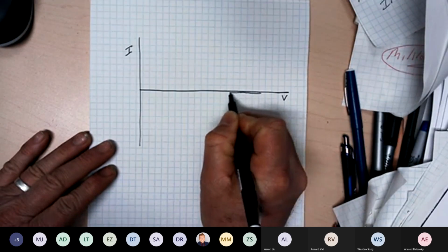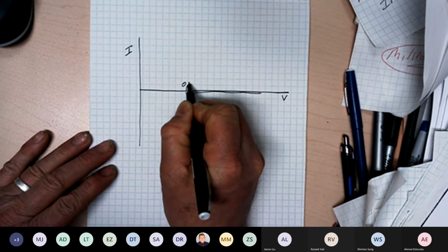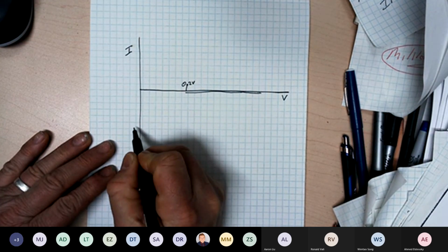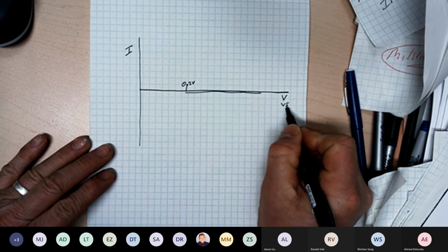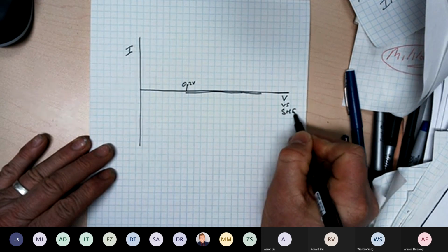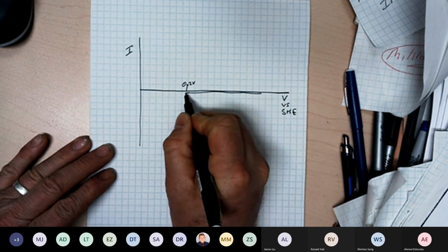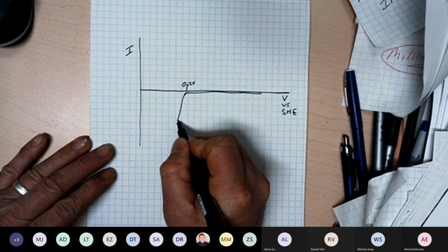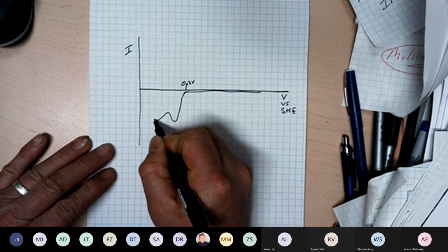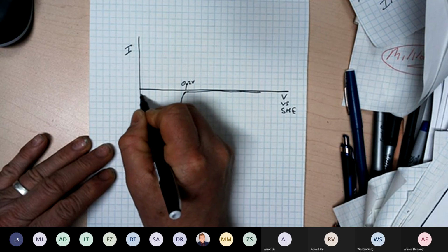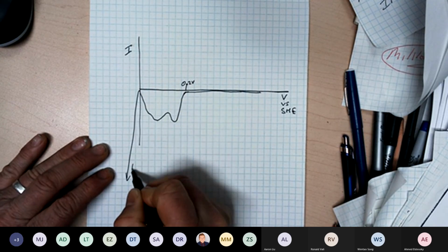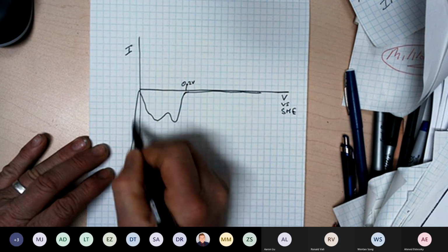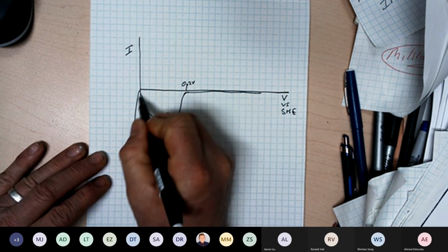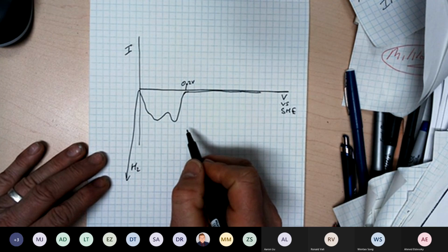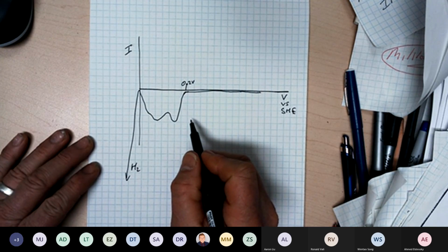It basically does nothing until you get down to around 0.2 volts. This is versus the standard hydrogen electrode. And then you see stuff happening. You see a nice signal, whatever it looks like. And if you keep going, then it shoots up like this because that's hydrogen evolution. When you go below 0 volts, you evolve hydrogen. And what this is, is under potential deposition of hydrogen, H2, on the surface of platinum.